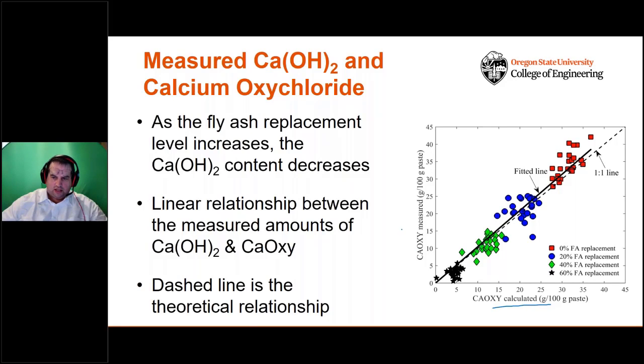Not shockingly here, we have the ability to predict or calculate the calcium oxychloride based on mixture composition and reactions. We can measure it. The good news is they fall along a 1-to-1 line or really, really close to a 1-to-1 line. The big thing that I want to point out is when you have no fly ash, you've got lots of oxychloride. As you add more and more fly ash to the system, the amount of oxychloride goes down to very, very manageable levels.